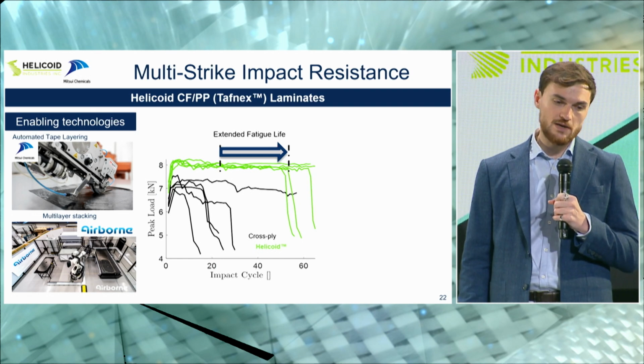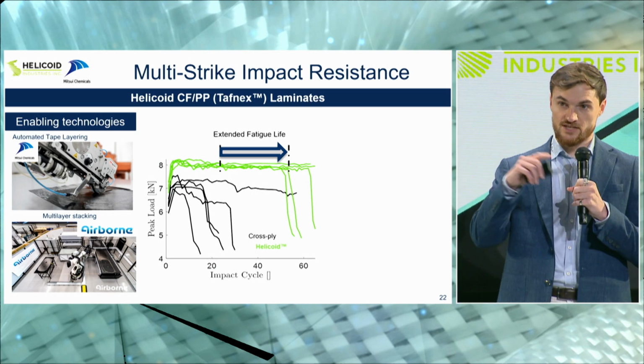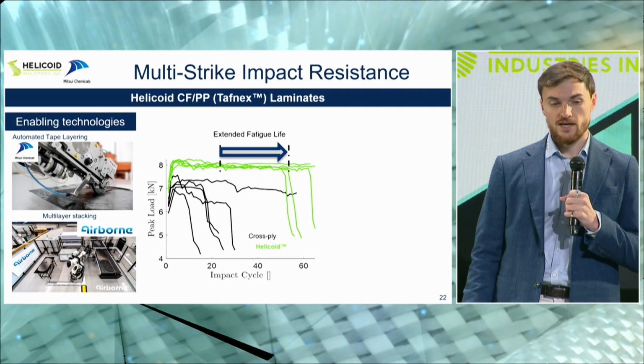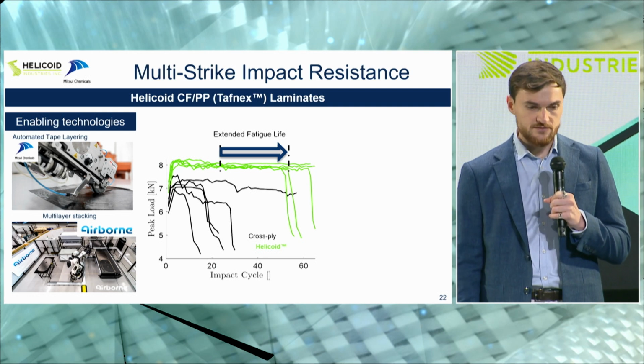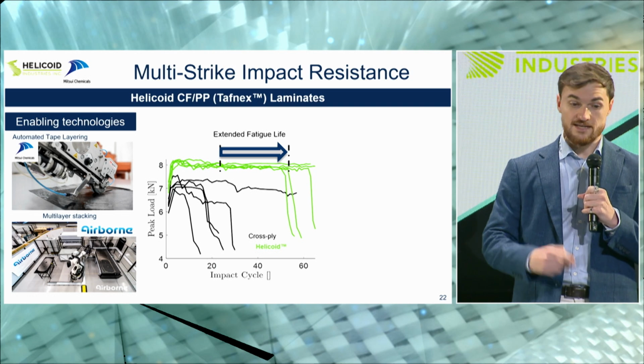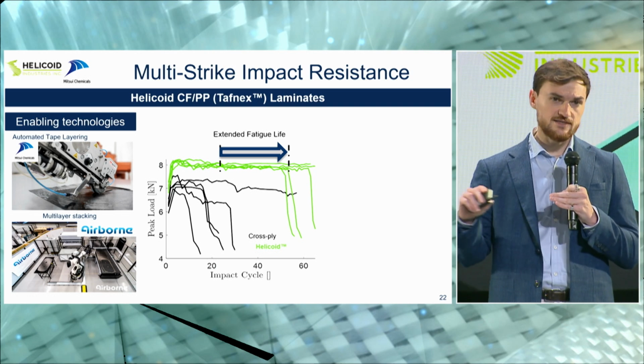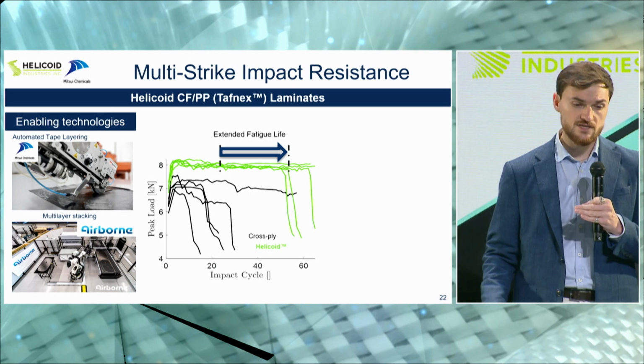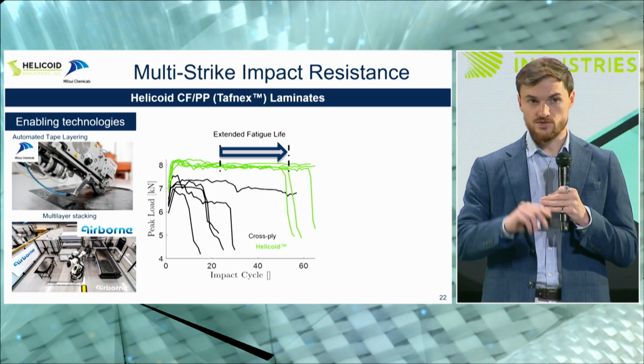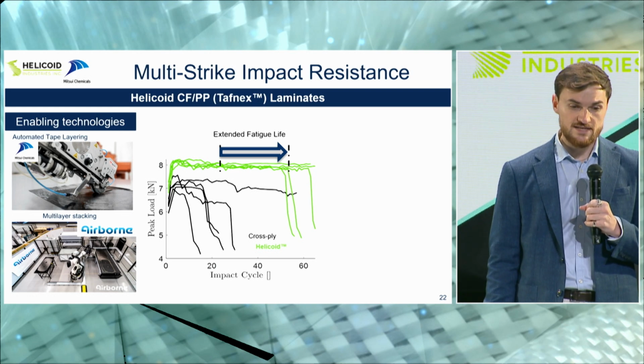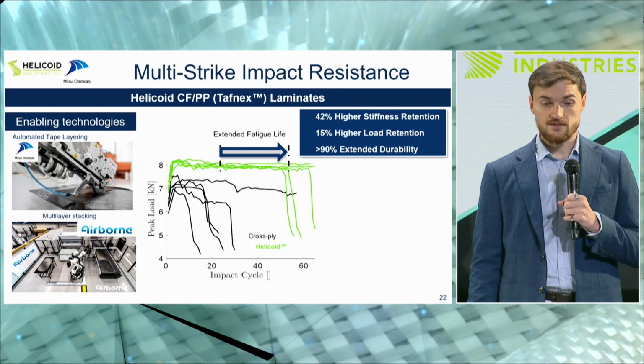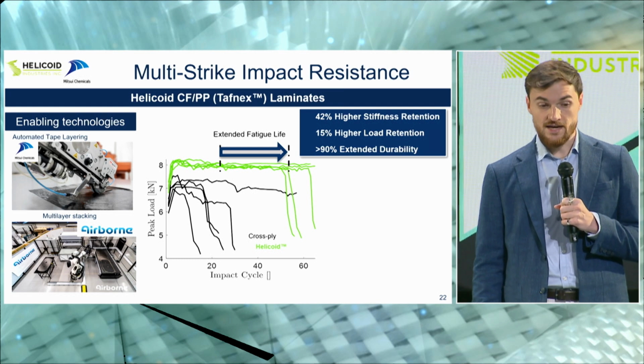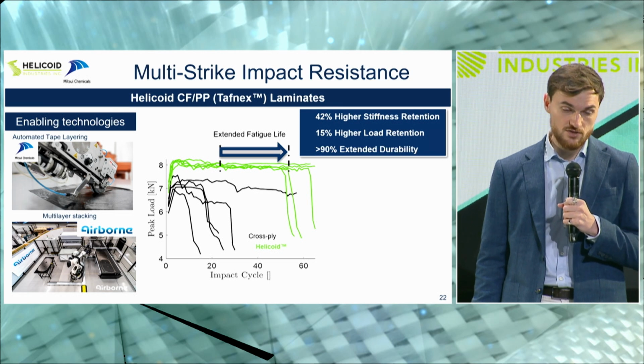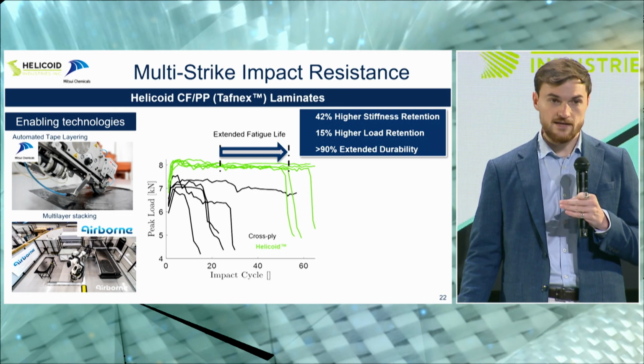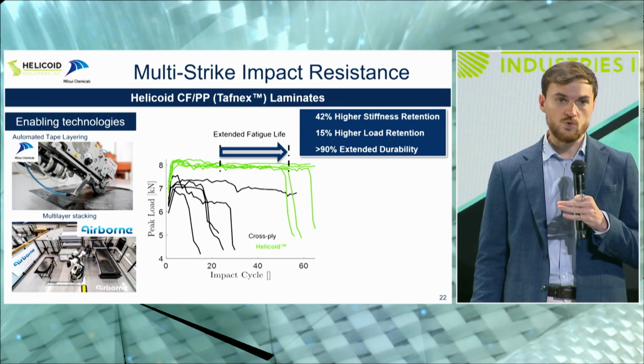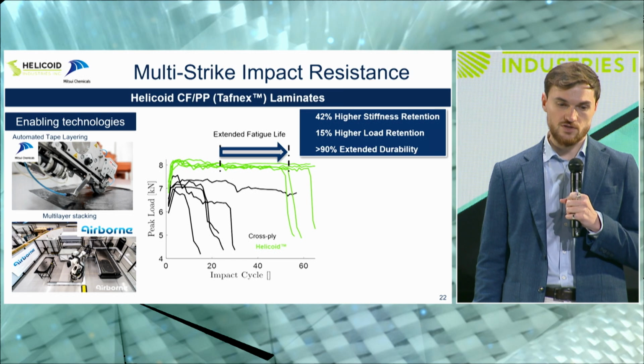You will see in black the cross-ply. In this case, we measured the maximum load reached at each impact, over the impact cycles. And you see how quickly they degrade in performance after only 20, 25 impacts. But the helicoid in green, you can see how steady they maintain the high performance over the impact cycles. And only after more than 60 cycles, you see a loss in performance. So we were able to extend more than 90% the durability of this composite, and also have a 42% higher stiffness retention, 15% higher load retention. Again, just changing the layup and having a more optimized layup that departs from the conventional way of designing composites.